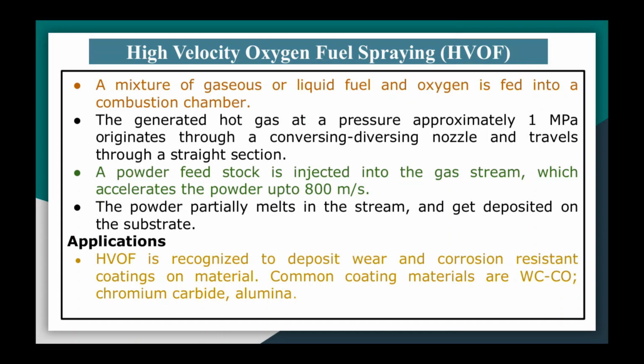The generated hot gas at a pressure of approximately 1 megapascal originates through a converging diverging nozzle and travels through a straight section, and the velocity of gases at the exit of the barrel exceeds the velocity of sound, and a powder feedstock is injected into the gas stream, which accelerates the powder up to 800 meters per second. The stream of hot gas and the powder is directed toward the surface to be coated, and the powder partially melts in the stream and gets deposited on the substrate.